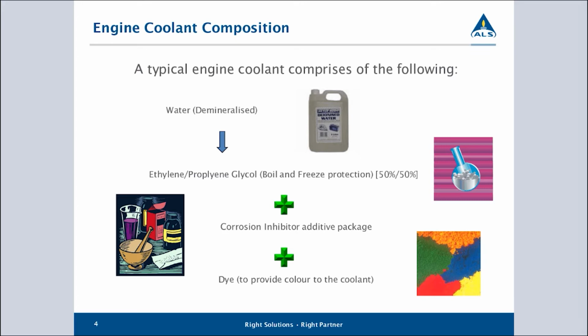We will then add our inhibitor package. If it's a conventional coolant, we'll be using our sacrificial additives. If it is an organic acid coolant, it will be using the organic acid inhibitors, or a combination of both. Increasingly, we're seeing these hybrid coolants becoming the dominant coolant type being used now. And then lastly, we put a dye into the coolant, purely to give it an identifiable color. There is a range of different colors that coolants can be dyed, but the dye itself doesn't provide any benefit to the coolant. It's merely a means of giving it a specific color so that we can identify it.